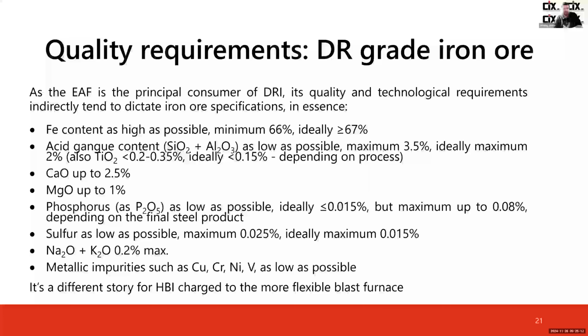One of the more concerning factors is the availability of DR grade iron ore. So typically most of the DRI is projected to be used in the EAF. And so ideally we want a very, very high iron content in the material that we have to produce the pellets. We want the acid gangue content to be as low as possible. Okay, and this impacts the more silicon alumina you have in your pellets. The problem is that you typically use almost 1.5 tons of pellets to produce 1 ton of DRI or HBI. So what happens is if you had 2% silica in the incoming pellets, you would have 3% silica in the product. And then this silica and alumina, when the DRI melts in the furnace,